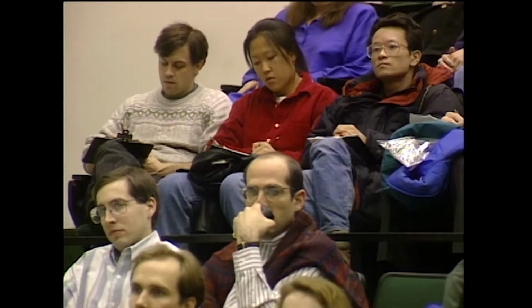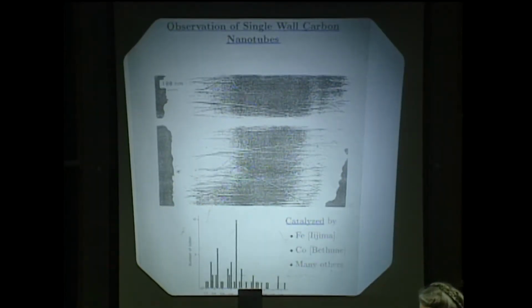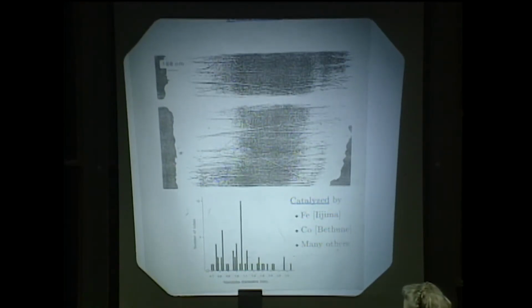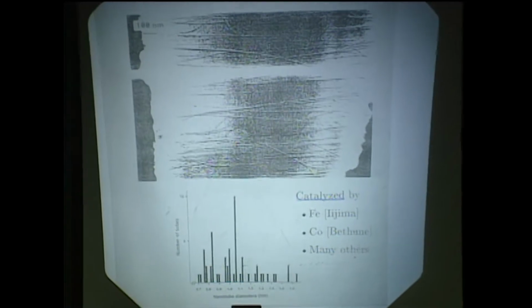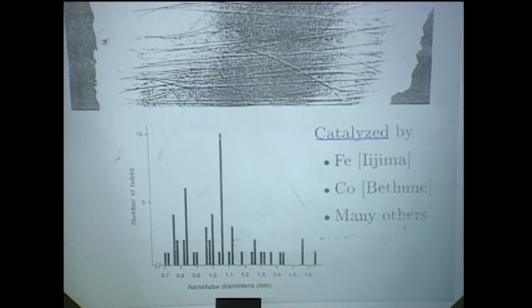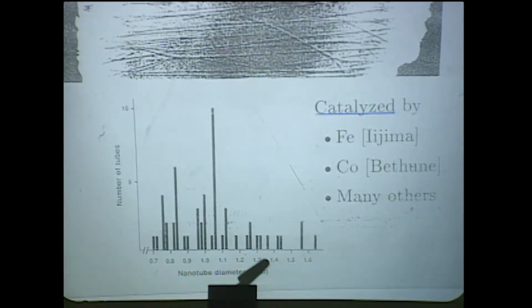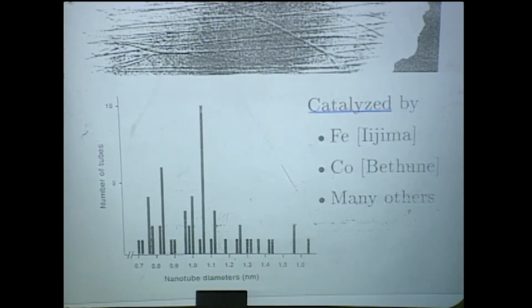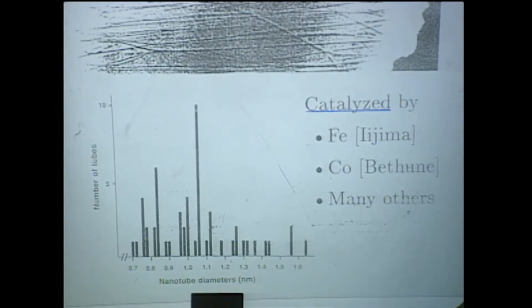Now, the theoretical work that was done in our lab here at MIT and around the world is almost all for single-wall tubes because those are the easiest to discuss. So there was some impetus to the experimental community to come up with single-wall nanotubes. And sure enough, within a year, they came up with them. So here are single-wall nanotubes, and they're made with catalysts, transition metals. The bar chart on the bottom of this viewgraph is very interesting because it shows that for the single-wall nanotubes, the largest diameters are very small. They're less than 2 nanometers. There are hardly any beyond 2 nanometers.